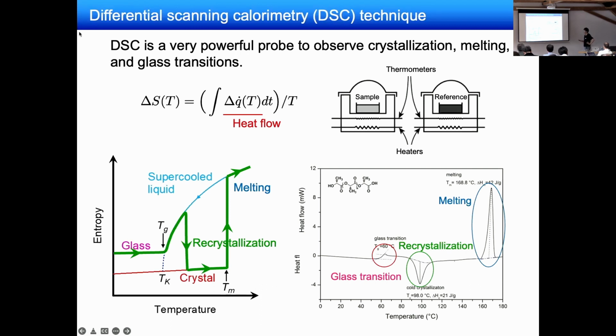In the DSC measurement, you prepare a sample and a reference, and you see the temperature of them. If there is a transition, you should have a temperature difference between them. But in this technique, the heat flow is supplied to compensate the temperature difference between them. Then you can calculate the entropy change at the transition from the heat flow you supply by using this equation.